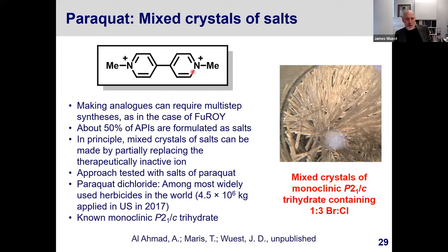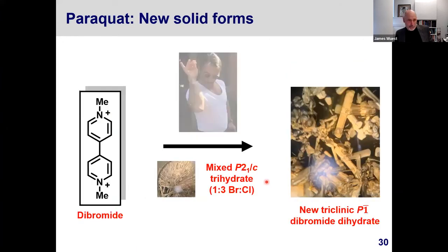And we've shown that this form allows us to make mixed crystals containing a 1:3 ratio of bromide to chloride. So bromide is introduced at a certain level. And we've been able to use those mixed crystals to seed the crystallization of the dibromide in a form that had not been reported before. So that tends to suggest that this use of ionic analogs may be an effective solution to the problem of the need to avoid complicated syntheses.